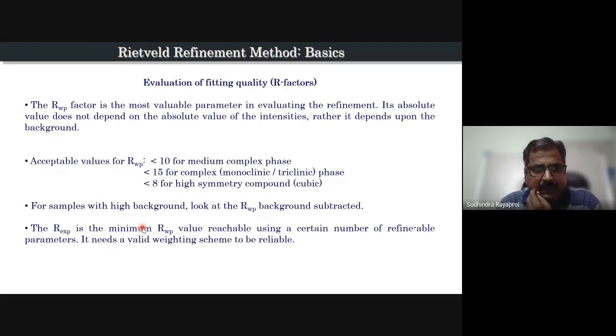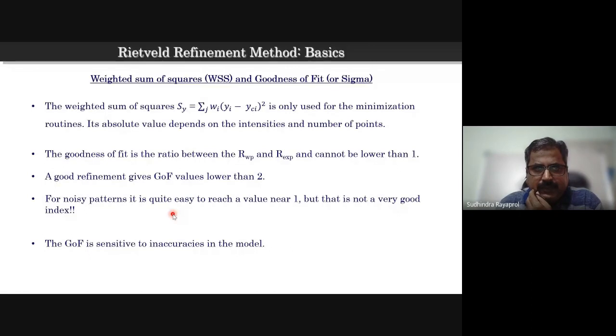Okay, so there are certain points, like samples with high background can have very high RWP values. And R expected, as I mentioned, is the minimum value RWP can reach. And so S or chi-square less than 1 has no meaning as such. It can be 1 or less. In ideal cases, it will be less than 2, or between 2 and 5. Okay, that's okay. So the weighted sum of squares is again the sum of the squares with some weighting scheme of the observed and calculated pattern, which is our chi-square.